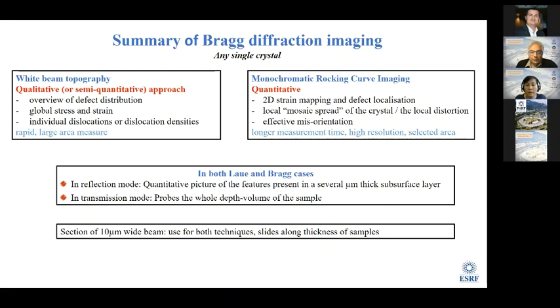And we also have another technique called section topography, when we use a very narrow beam of 10 micron. This can be used for both techniques, and in that case we can see a slice along the thickness of the sample. For this one, we can send several beams at the same time, then you can have the information at different places along the thickness of the sample.